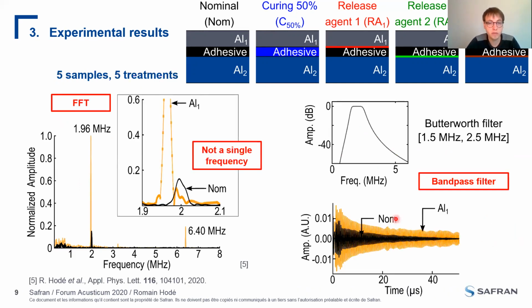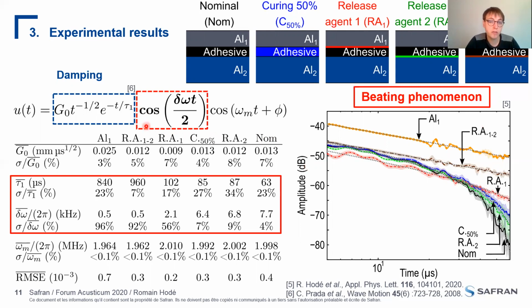But when we come back to the first observation, that here we don't have a clear resonance frequency, but it's more like we have two really close resonance frequencies, we can add this to the theoretical model with a cosine function, which is due to the beating phenomenon between two really close frequencies. And these frequencies are separated by the factor delta omega. And what we can see is that we have a better agreement between the theory and the experimental measurements. And notably, we can access two interesting metrics, which are τ1 and delta omega, that can be identified with these experimental attenuations. We can notably see that for the nominal case, the parameter τ1 is the lowest and the parameter delta omega is the highest compared to the case, for example, of an aluminum plate.